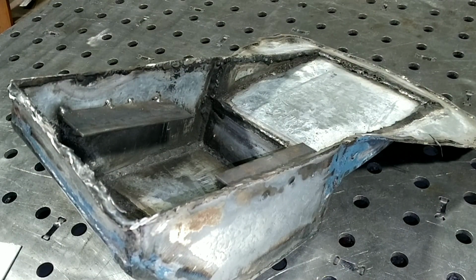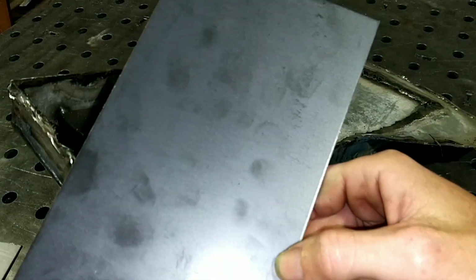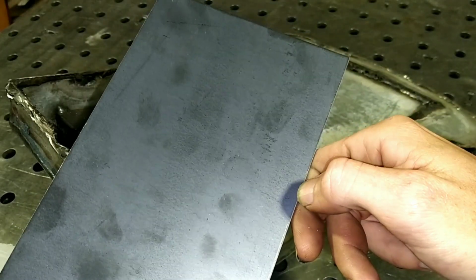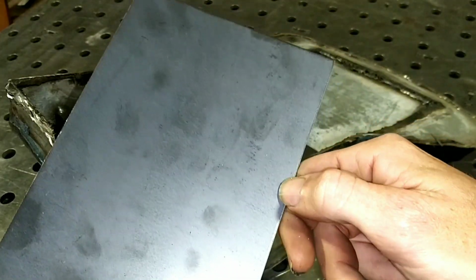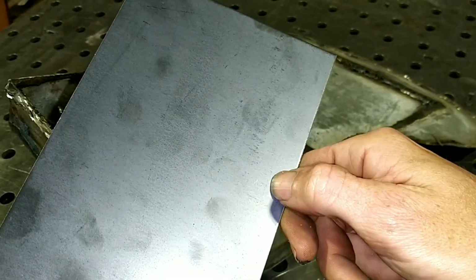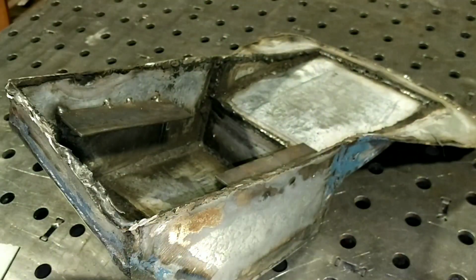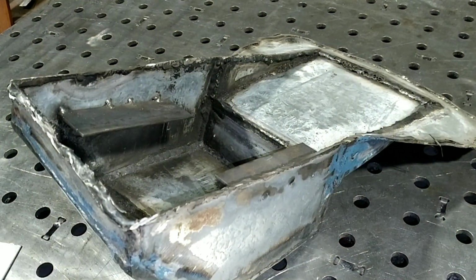It's not going to matter because what we'll end up doing is taking the black oxide layer off. We'll take this off where we're going to weld it, not over the entire surface, just where the fusion zone is. And that will allow us to weld beautiful and clean with no inclusions, no porosity, no problems.